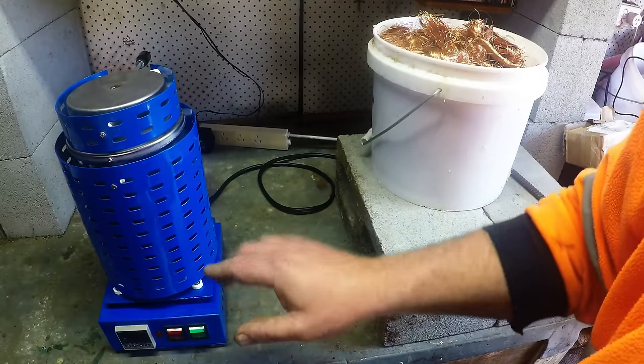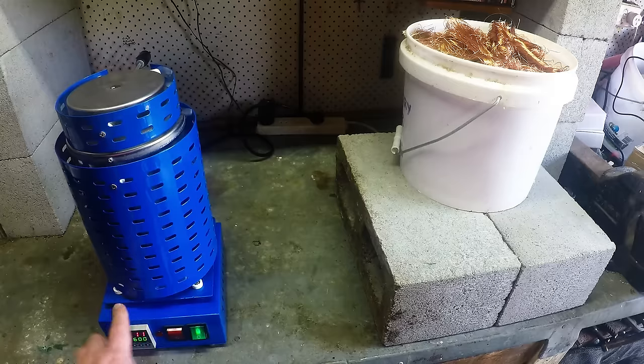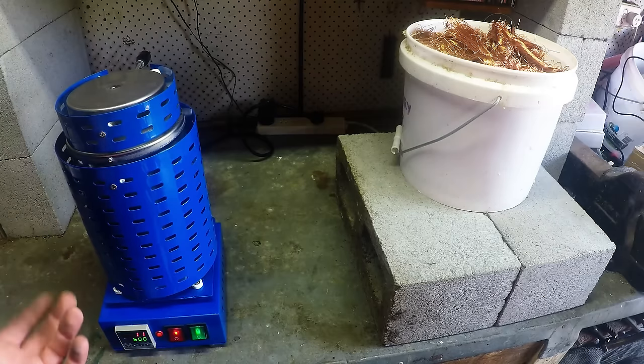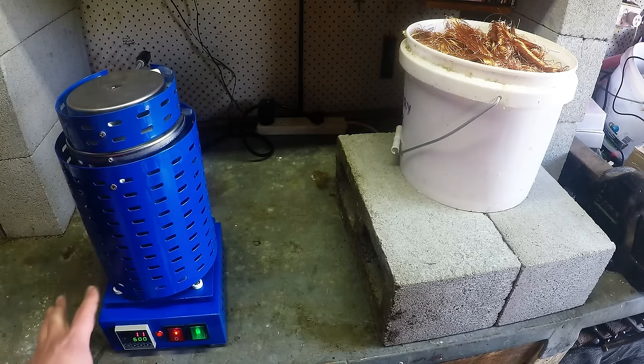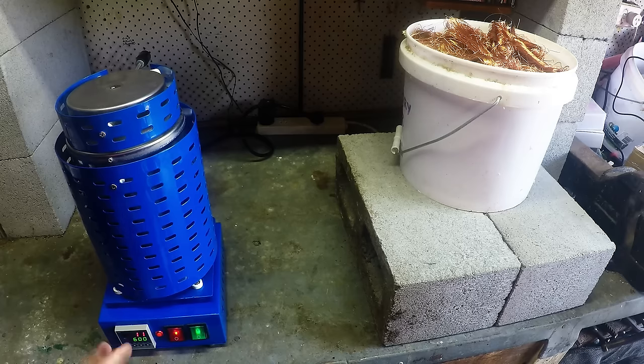I'm just going to turn this on and let it heat up. I'm just setting this up now to temperature. They recommend, instead of going right up to the temperature on these electric ones, to first bring it up in stages. So I want to get it to 1160 in the end, but I'll start it off at 600. Once it stabilizes at 600 degrees Celsius, then I'll bring it up another increment - I'll probably bring it straight up to 1160. This is a newer model, and this version actually heats up a lot quicker than the older version. So it should only be 10 to 15 minutes and we should get this right up to temperature.